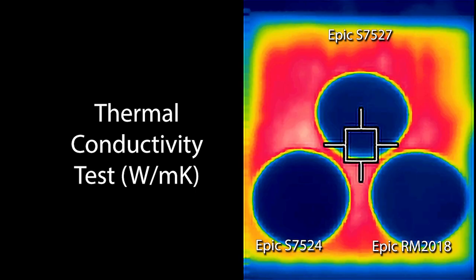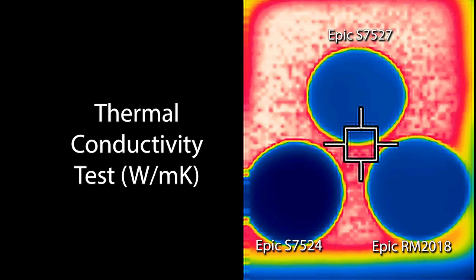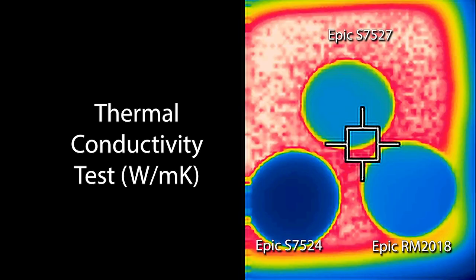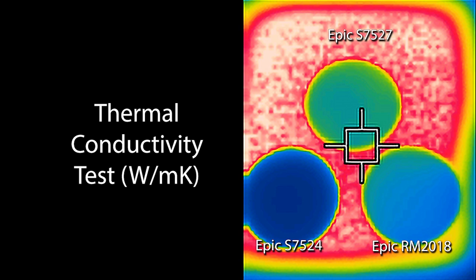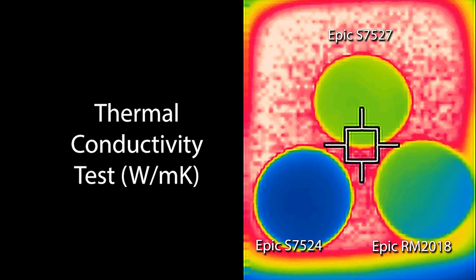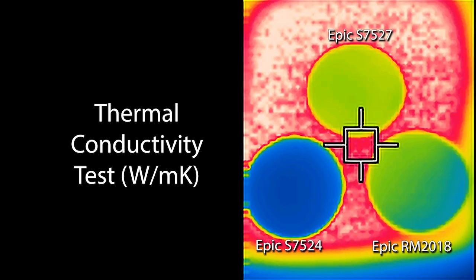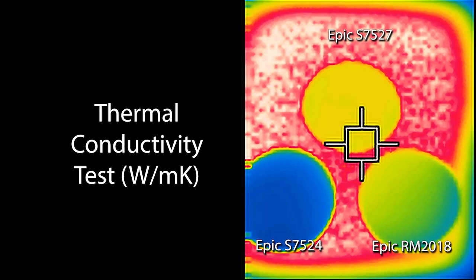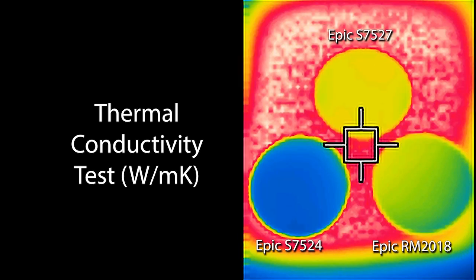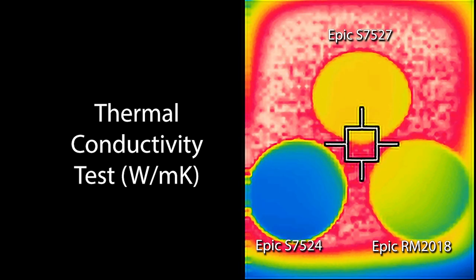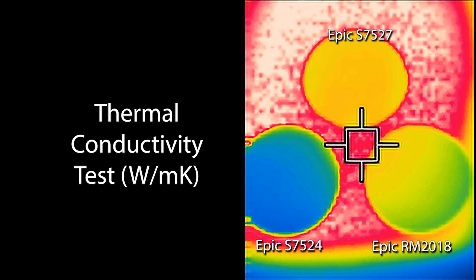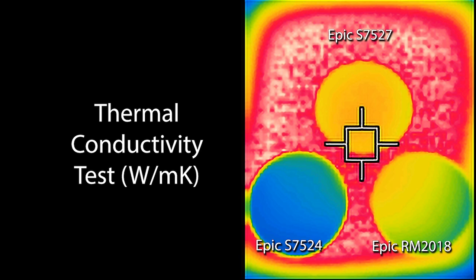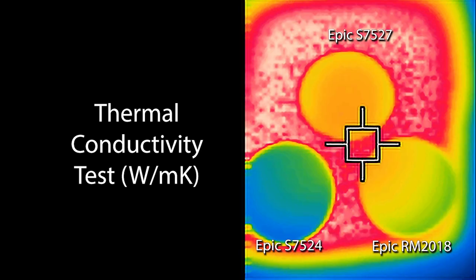S7524 on the bottom left has low thermal conductivity. RM 2018 on the bottom right has medium thermal conductivity. S7527 on the top has high thermal conductivity. The infrared image shows as the pucks are heated from the bottom, you can see that the S7527 gets hot faster than the other two, indicated by the yellow color. Obviously, this shows it is pulling heat from the hot plate faster than the S7524 and the RM 2018.